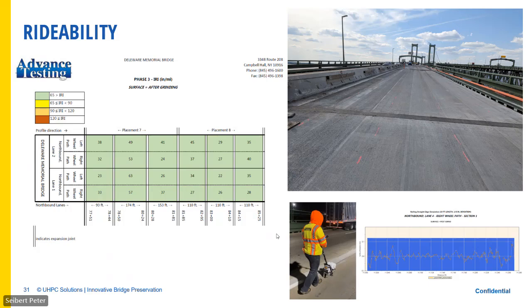Some of these profiling machines kind of work off of averaging out the bumps that are there. And when you do a quick pass, not trying to take a lot off the top, you're able to take off some of the little small undulations, and then the next pass takes your 1/4 inch production removal off. And we wound up at IRIs, I mean, this is phase 3, as low as 22 of an IRI. Everything lower than 65, which is an incredibly smooth ride. So if you do drive across this bridge going northbound and you ride in the 2 right lanes, you'll find that it's a very, very smooth ride for you.